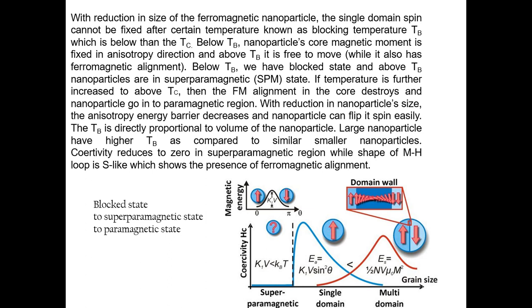There is also a dependence on the applied temperature at which we are working. Every nanoparticle has a certain temperature — the blocking temperature Tb — above which they behave as superparamagnetic, and below which the core spin can be parked in a certain direction. In both the blocked and superparamagnetic states we are still below Tc. Below Tb, the nanoparticle's core magnetic moment is fixed in an anisotropy direction; above Tb it is free to move and we are in the superparamagnetic state.